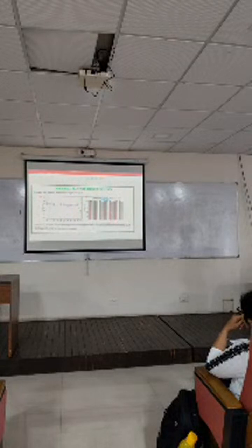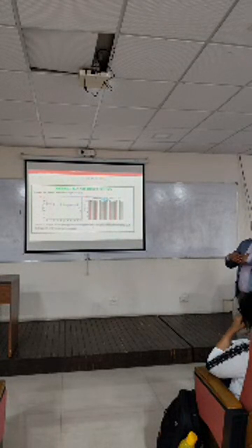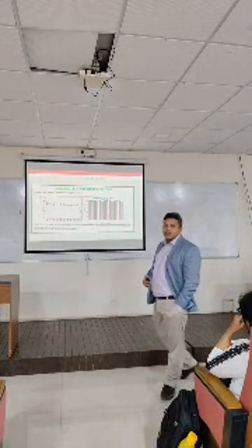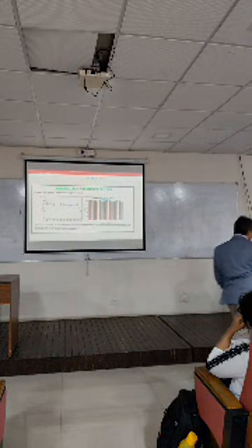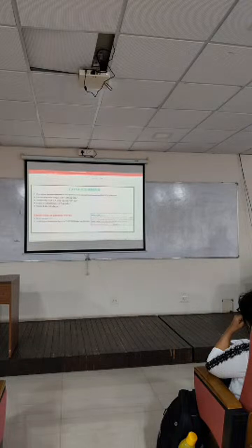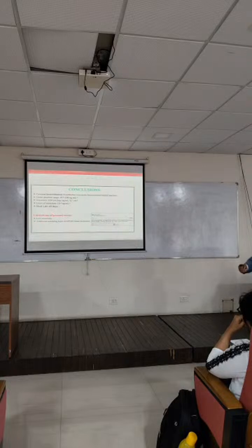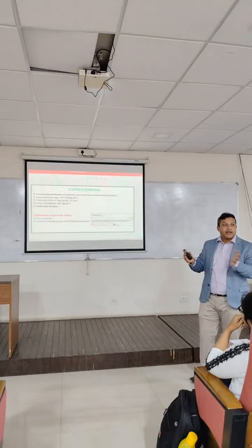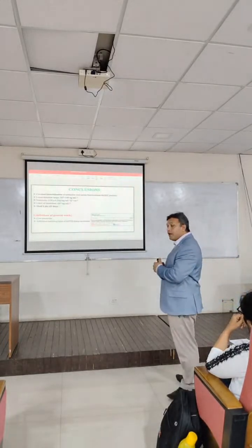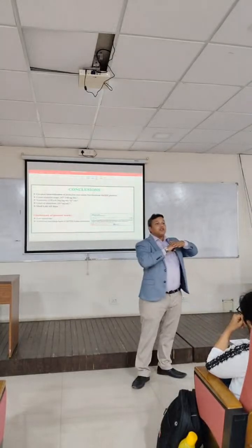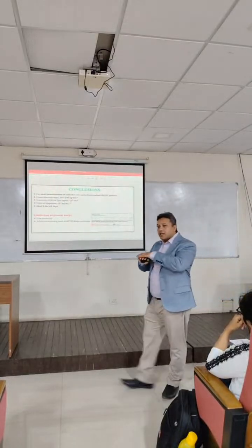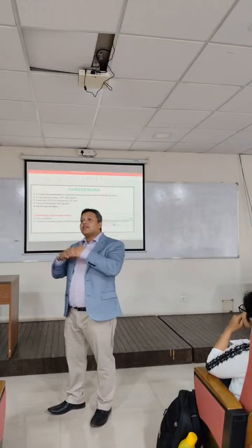So with respect to the previous one, we have observed some good properties in terms of shelf life and real sample analysis, but there are also some limitations. One limitation is low sensitivity. Compared with the previous ones, which were 30.8 and 13.2, this one is 0.961. So sensitivity is one of the issues. Why? Because we have added an additional insulating APTS layer. On this basis our sensitivity decreased, but it shows increased shelf life.